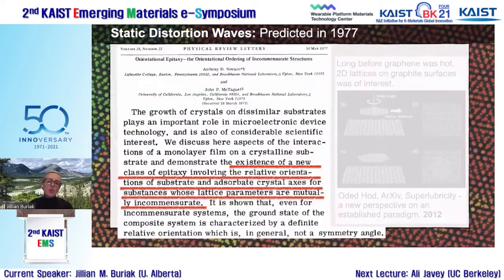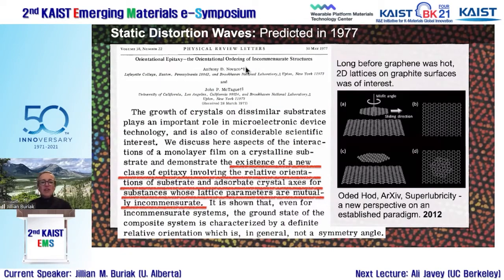And so these static distortion waves actually go back to, they were predicted in 1977 in a Physical Review Letters paper. And we're actually in contact with Anthony Novaco, which is really, really cool. So he's a professor emeritus, but he had predicted these. He and McTague had predicted them on graphite surfaces. So people say, well, graphene, that's so new, but we're talking PG here. And if you have a crystal of, say, xenon or some other inert gas, if they don't match, the system will adopt an angle of offset, just like what we're seeing, Moiré superstructures, but can actually adopt that little twist, that static distortion wave, in order to further lower the global energy.